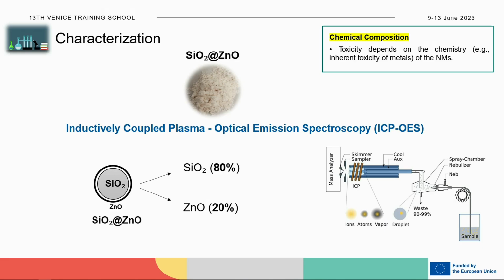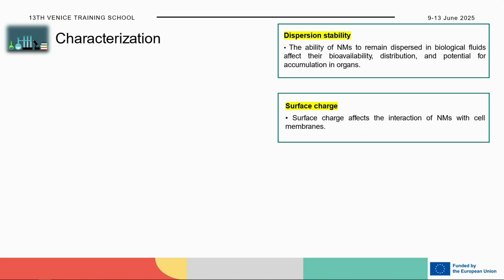And in this case, we managed to understand the composition of the two different components in our advanced material. The results showed us that we have around 80% of silica dioxide and then 20% of zinc oxide. On top, you cannot say from the ICP-OES, but we can say just the percentage of the two elements.